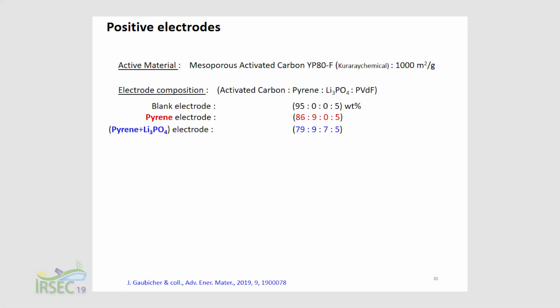So for the positive electrode, we have used a mesoporous activated carbon, which is very classical for lithium-ion capacitors. Nothing special. For the electrode composition we add some PVDF, 5 weight percent. In our electrode with the two additives, we use 9 weight percent pyrene and 7 weight percent lithium phosphate. And we have used a third electrode with only pyrene to compare.